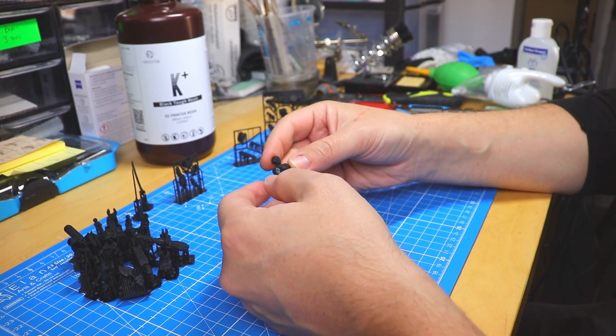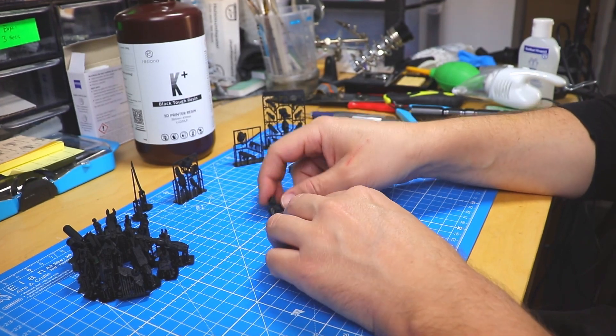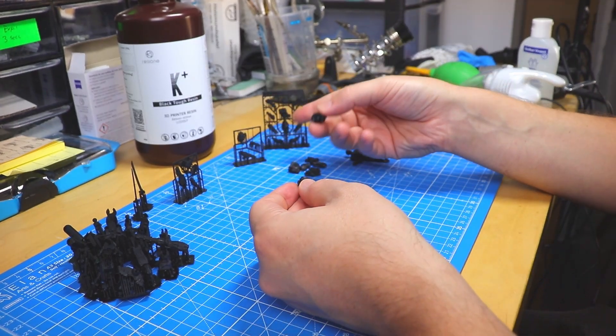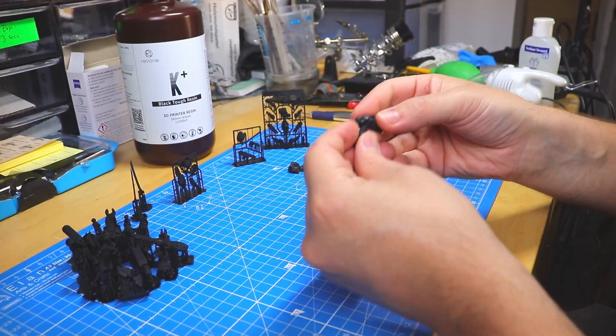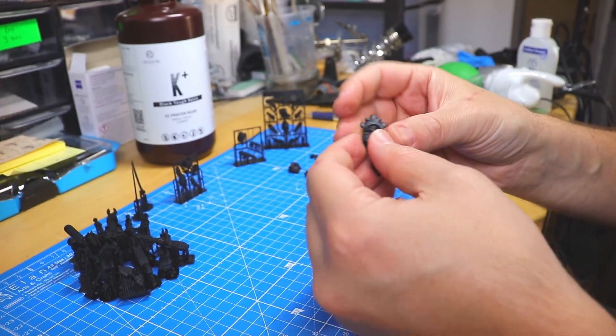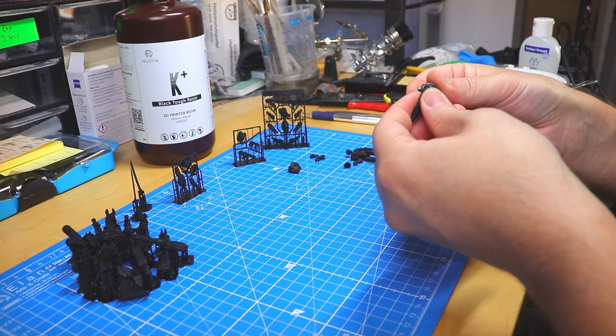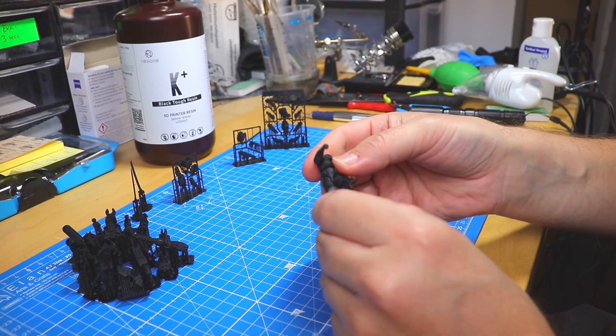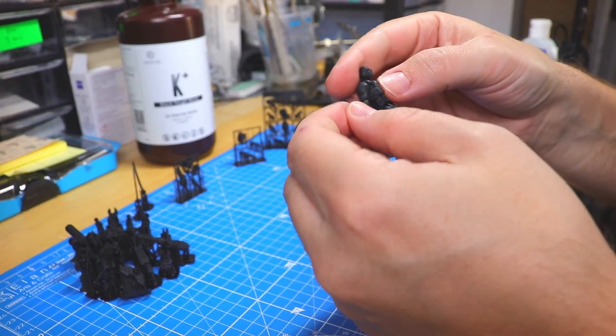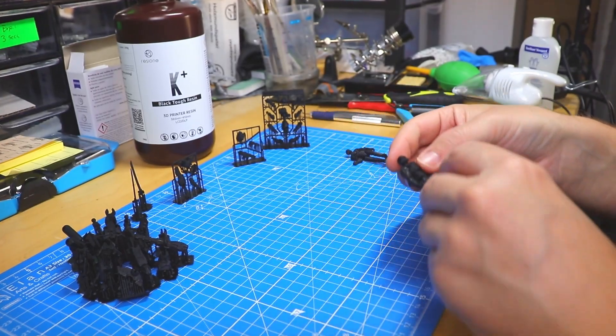This figure is a bit loose because I think the exposure is too low — it's a very dark resin, so it probably needs a longer layer exposure time. But the assembly went quite well overall. When fully hardened after a few days, the right side hip joint is really scratch-free. I would say it's a good measure to let prints dry for a day or two before assembling a snap-fit figure. Popping the parts in nicely — no surface scratching, dusting, or powdering so far. It's very good. I assume for this resin maybe four seconds layer exposure would give really nice tight joints overall.